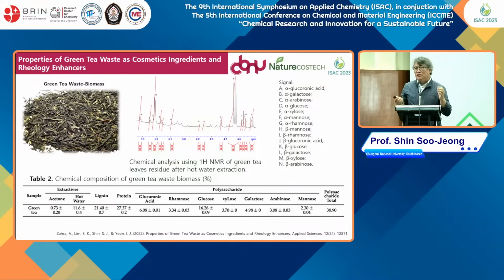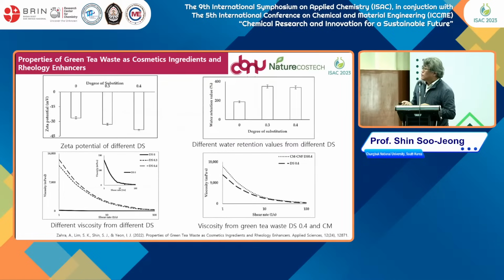They asked us for help because they make cosmetic products from tea leaves and generate a lot of tea residuals, so we tried to turn the tea residuals into nanoparticles. Monosaccharide analysis showed a lot of cellulose and pectin. With this raw material, cellulose nanofibrillation didn't go well, so we added extra carboxymethyl pretreatment, which increased zeta potential, and the carboxymethyl-pretreated cellulose nanofiber increased water holding ability and viscosity.